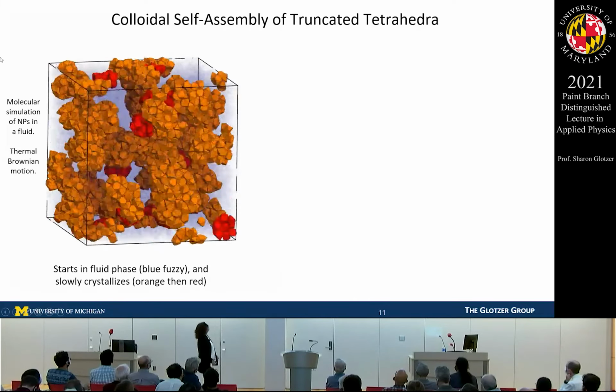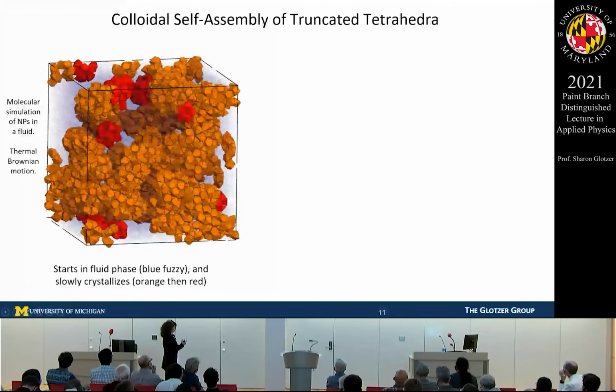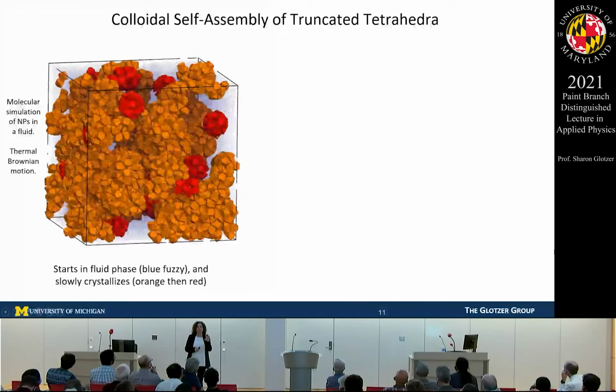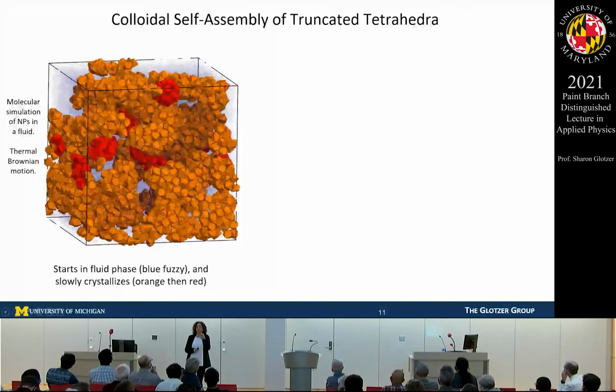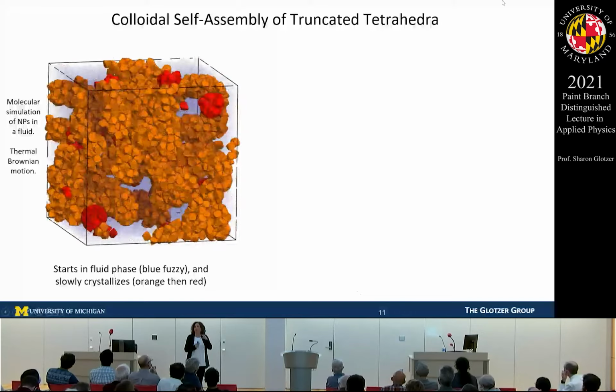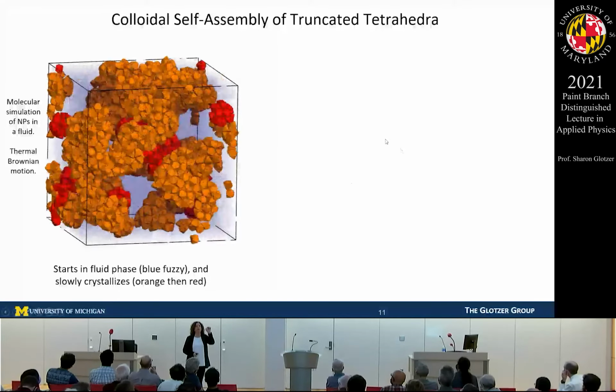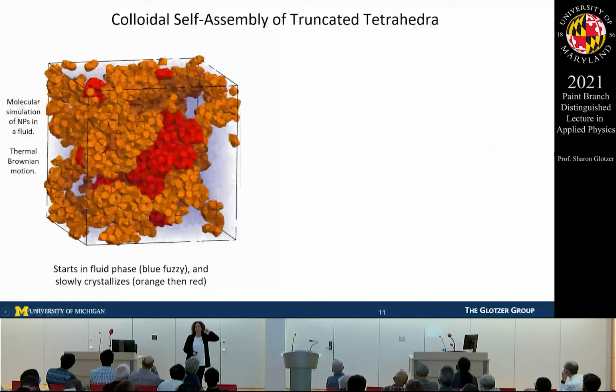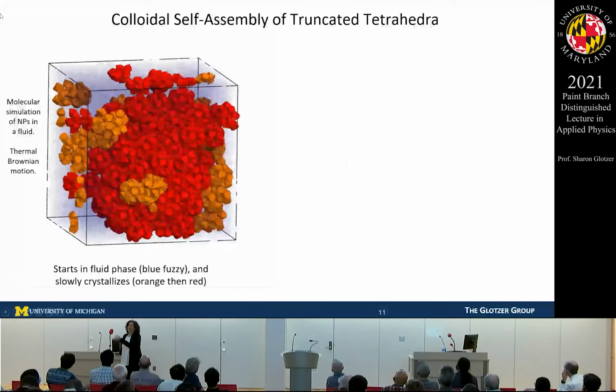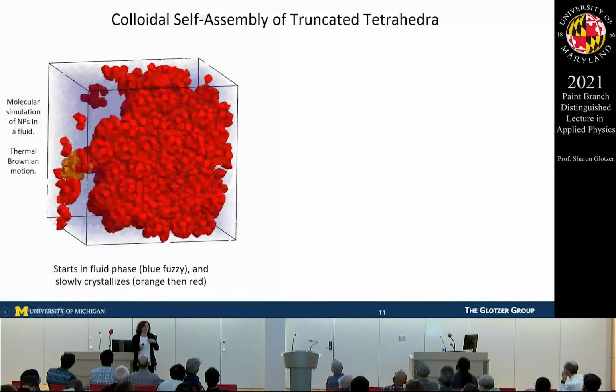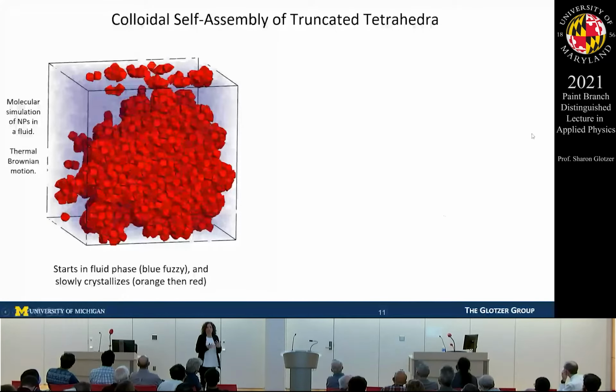Let me try to play that again. Play. Left click. Boom. And then you see that we color them orange when locally they seem to be in some kind of organized structure, but it's definitely not long-range structure. There's no long-range order in the system. Red are the ones that are at the end going to be in the crystal phase. So we can run it to the end, figure out what crystal it is, and then watch for when a particle is locally going to be part of the final crystal and color it red. So we can actually see the crystallization process.